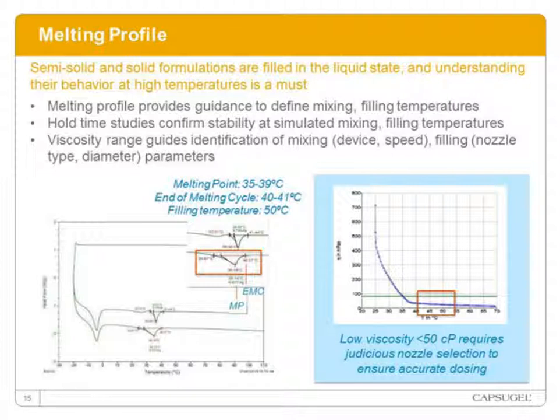In this particular case study, the melting point of this formulation was determined to be 35 or 39 depending on the cycle. However, the end of the melting cycle in either case was determined to be over 40 degrees, for which a filling temperature of 50 was identified.